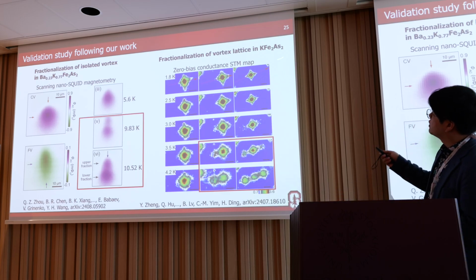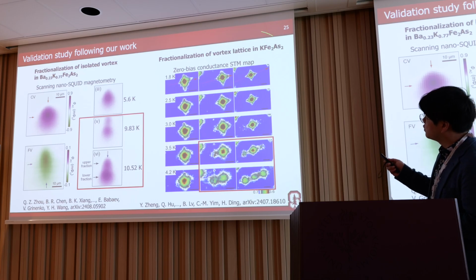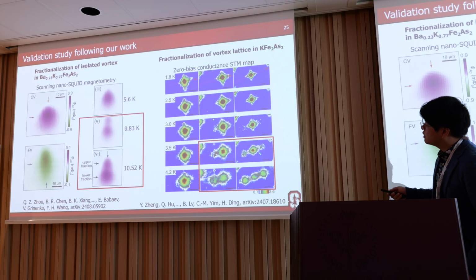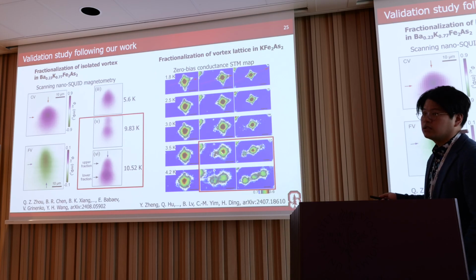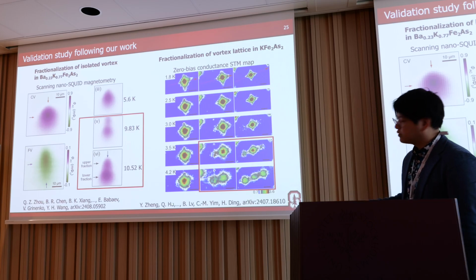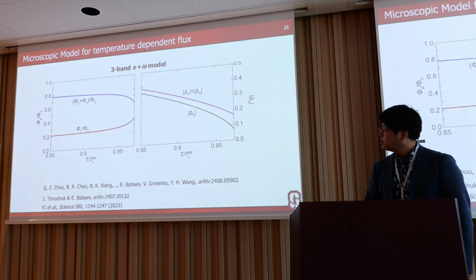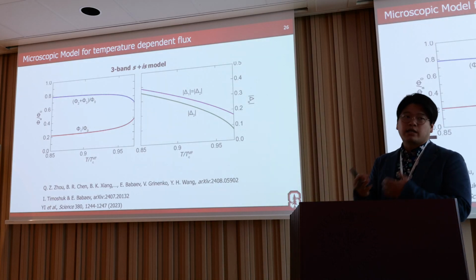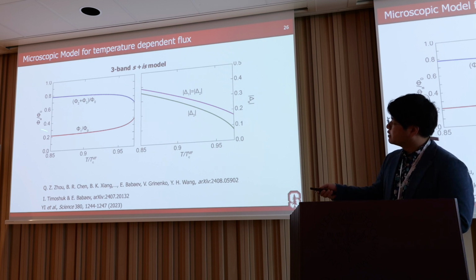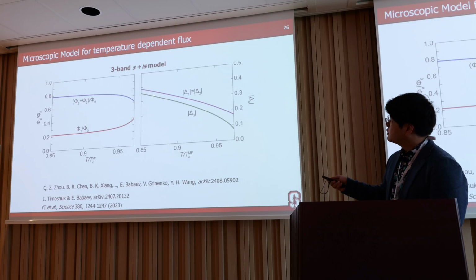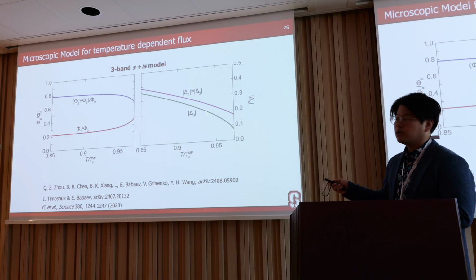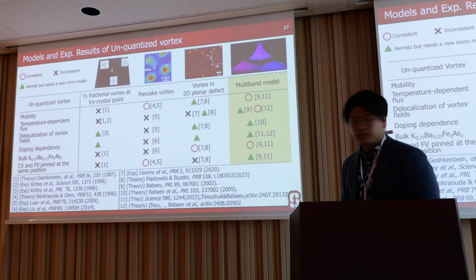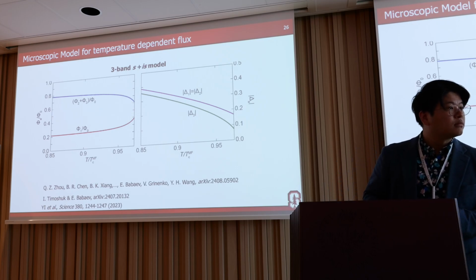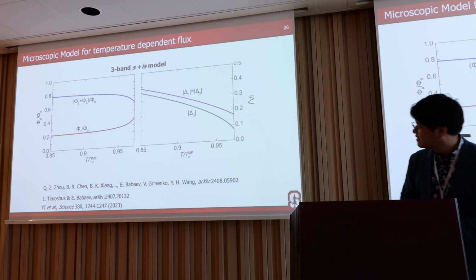And for the STM measurement, with different doping samples, they also see the fractionalization across the TC. We have a talk on this in this session later. Okay, and for the theory from Igor's group, the three-band S plus IS model now explains this temperature dependence of the fractions, using a very similar but slightly different temperature dependence of the gap. Actually, it's not technically from my group. I think Julien did this calculation. He is already a professor.